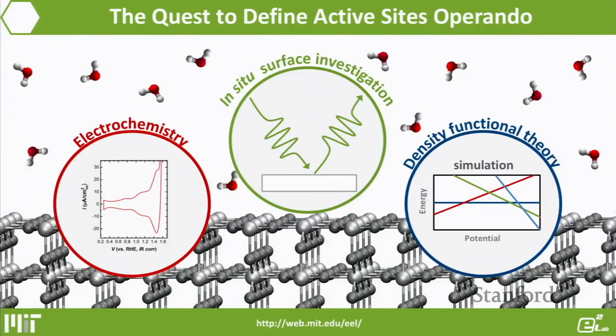So I want to end this presentation by coming back to the fundamentals. So far we have seen a correlation of bulk electronic structure to some surface activity. So one would argue, what are the active sites? How would we define active sites? Or how would the surface change its functional potential? And this is some investigation that we have been doing using single crystal surfaces, combining electrochemistry, in situ investigation, and the DFT. And this is also the work of Manuel, who's working at SUNCAT.